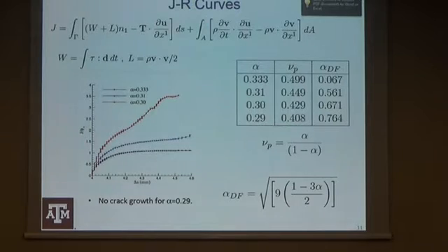So yes, it's like energy balancing when you have friction. Whatever's dissipated, you just add it in. But if you do that, now you can calculate JR curves, J resistance curve. So for an incompressible solid, basically it's steady, constant J crack growth. It's almost elastic. If the Griffith energy is 1, this is 1.1, something like that. You add a little bit of compressibility, you increase the crack growth resistance a little more, and it goes up enormously. That was a little bit of a surprise.